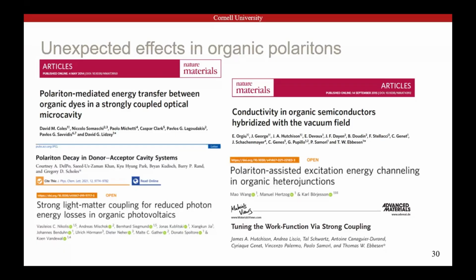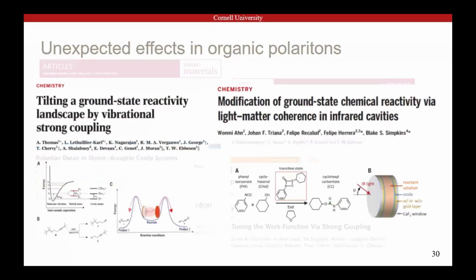What's really taken the field by storm in the last few years was the recognition if you form these polaritons by coupling to the infrared absorption bands of certain bonds, you can alter the rate and selectivity of certain thermally activated chemical reactions. Again, just by running the reaction between a pair of mirrors. Pretty wild. And this has created this massive hype about the idea of polaritonic chemistry, where you can use polaritons or strong coupling, some kind of selective catalyst to steer reactions and maybe steer photophysics in new directions.